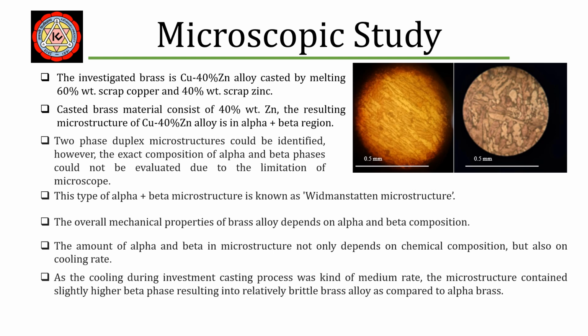A two-phase duplex microstructure could be identified. However, the exact composition of alpha and beta phase could not be evaluated due to the limitation of the microscope. So this type of alpha-beta microstructure is known as Widmanstätten microstructure.